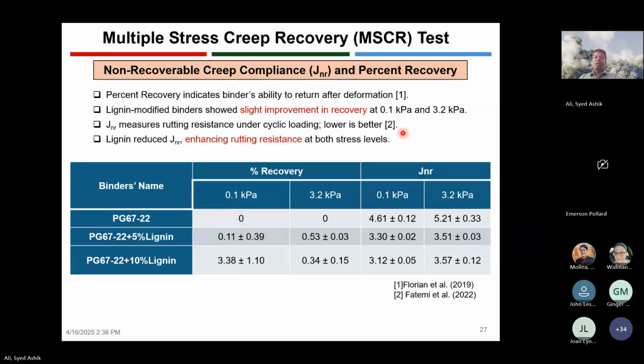Okay. So we did an MSCR test, or multiple stress creep recovery test, on a lignin modified binder. The two parameters that we looked at from the MSCR test were JNR, or non-recoverable creep compliance, and percent recovery. Generally, percent recovery indicates the binder's ability to return after deformation. This is the elastic property. It represents the elastic property of the asphalt binder. And we found that although lignin is not a polymer modifier, it increased the recovery a little bit, not much.